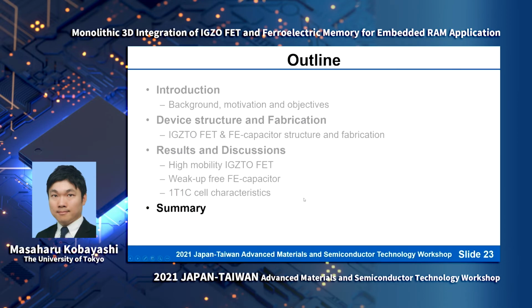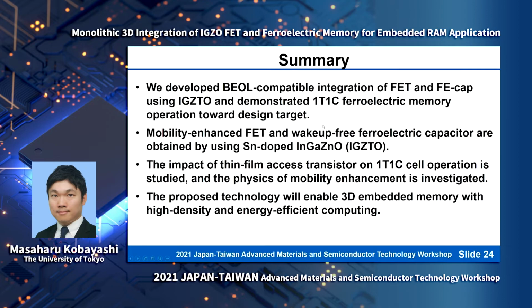Let me summarize my presentation. We developed a backend process compatible integration scheme of the FET access transistor and a ferroelectric capacitor using tin-doped IGZO material, IGZTO, and demonstrated 1T1C ferroelectric memory operation toward the design target. The mobility enhanced FET and the wake-up-free ferroelectric capacitor are obtained by using tin-doped IGZTO. The impact of thin film access transistor on 1T1C cell operation is studied, and the physics of mobility enhancement is also investigated. So we believe that the proposed technology of 3D monolithic integration will enable 3D embedded memory with high density and energy efficient computing.